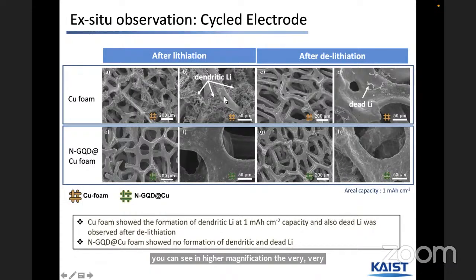And then after delithiation, some part of this has dissolved and gone, but you can still see some trace of this lithium, which we call dead lithium. We just stripped out 100%, but there is still material remaining. This is typically dead lithium.